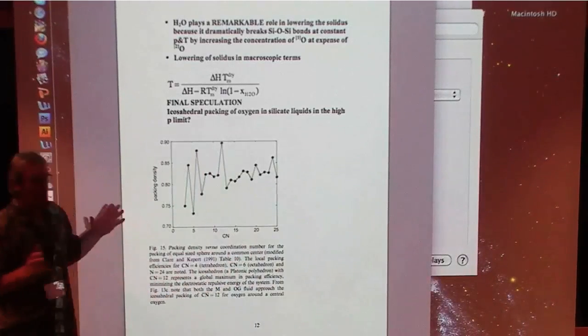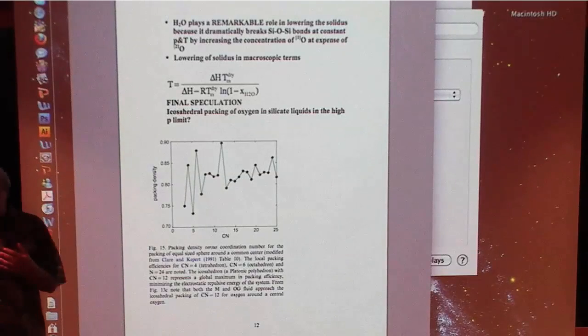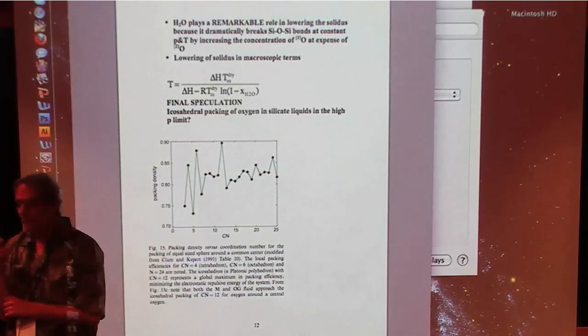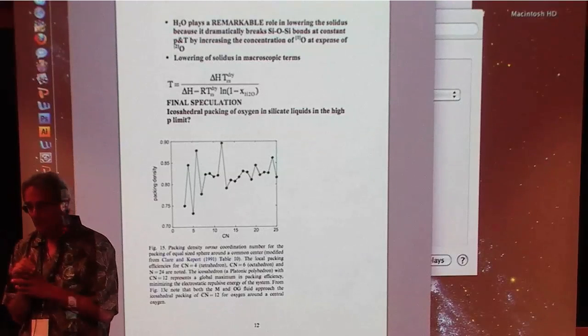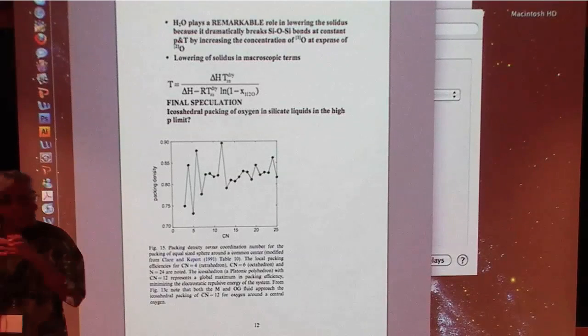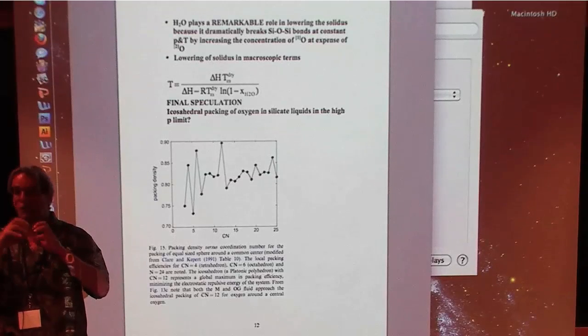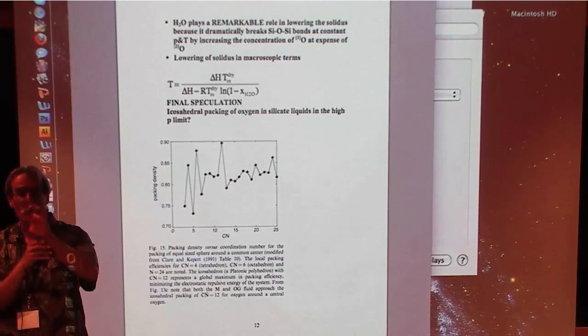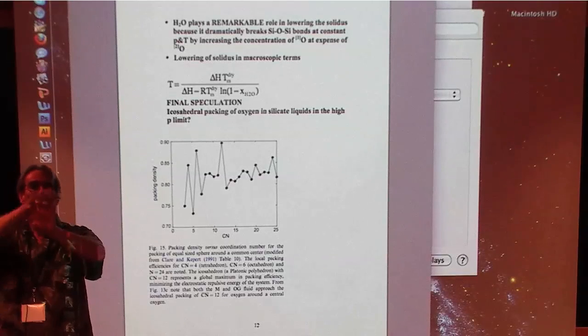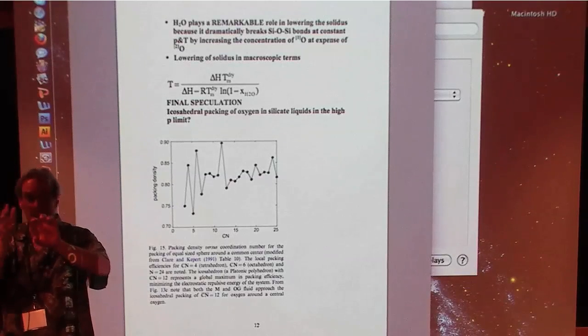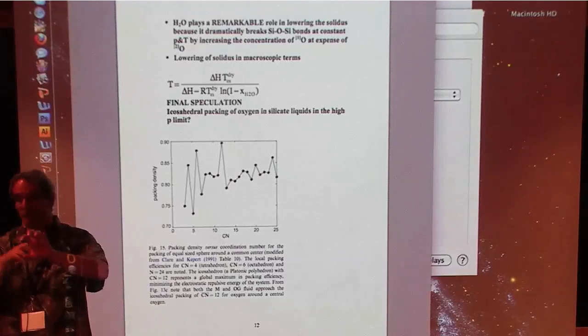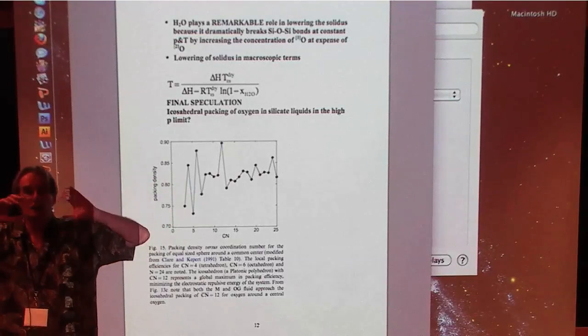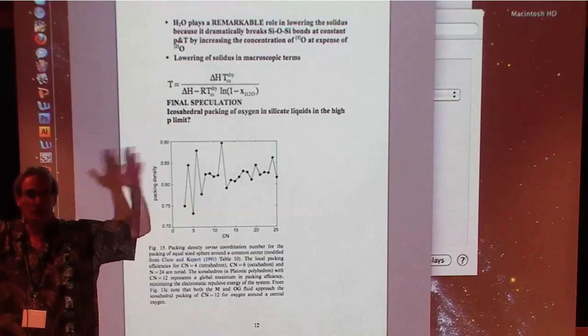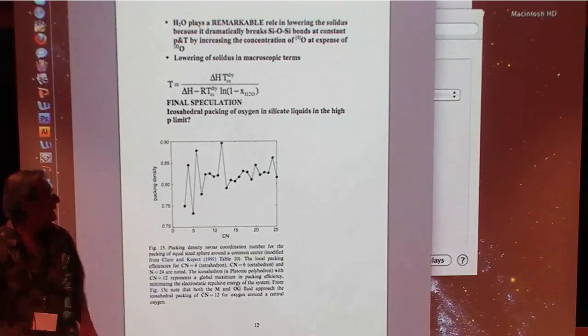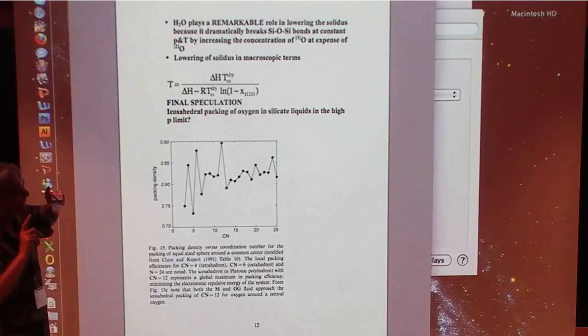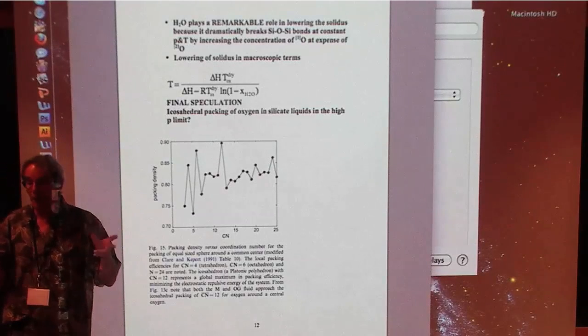Here's a hypothesis, a conjecture. When we do these neutron diffraction experiments, we notice something as we go to really high pressures. The beautiful thing about ND is that you can look at the structure of the melt. You can look at an oxygen and ask how many nearest neighbors of oxygen it has, or how many of magnesium, of silicon, whatever. You know in Euclidean space the location of every atom of your 100,000 atoms, and it's easy to figure that out. And keep in mind that silicates are 90% by volume oxygen.